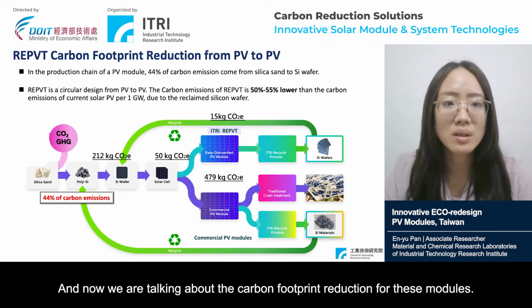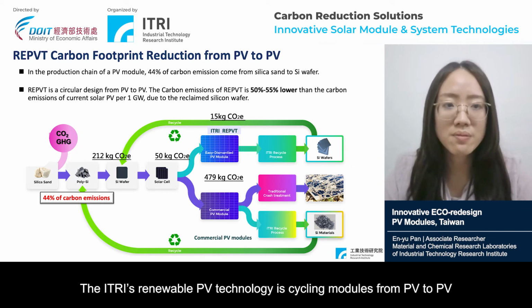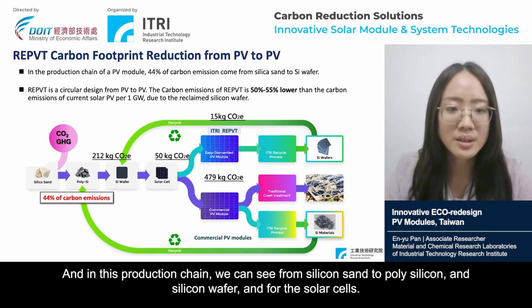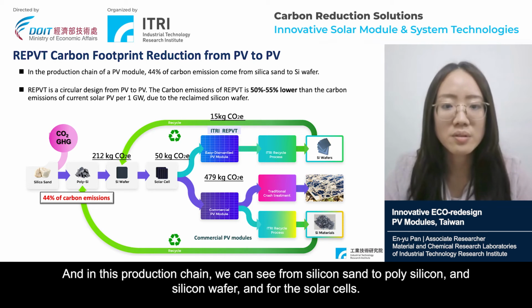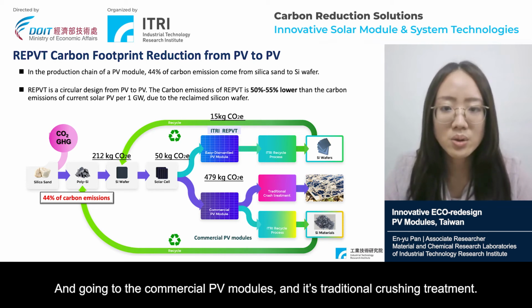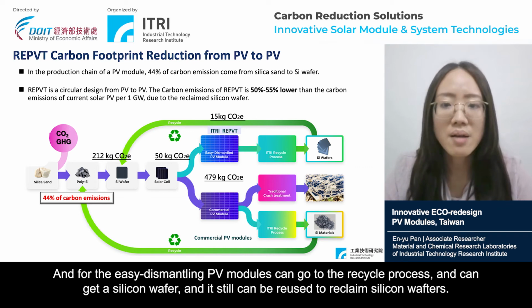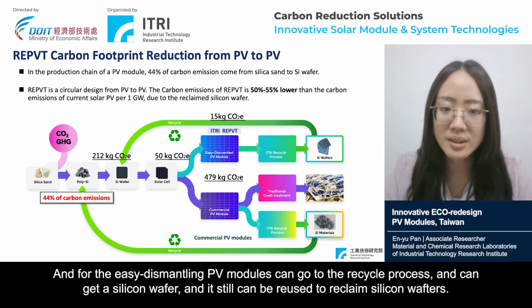And now we are talking about the carbon footprint reduction for these modules. The ITRI's renewable PV technology is cycling modules from PV to PV. In these production chains, we can see from silicon sand to polysilicon, the silicon wafer, and the solar cells. And going to the commercial PV modules, it's a traditional crush treatment. And for the easily dismantled PV modules, it can go to the recycling process and get a silicon wafer, and this can be reused for the reclaimed silicon wafers.